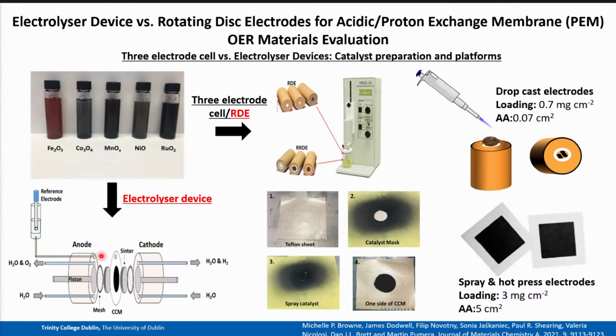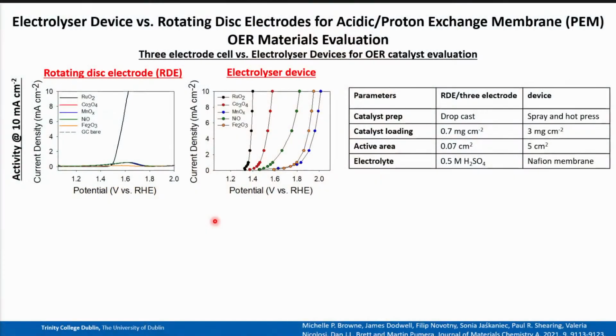So to directly compare the OER, so the anodic side of our electrolyzer device, to a rotating disc electrode, we used a reference electrode. So we were purposely just measuring the OER in the electrolyzer device. So for the results that I show you here, for your activity at 10 milliamps in the rotating disc electrode setup, essentially what we can see is that the ruthenium dioxide, which is also known as the state of the art, performs pretty well. However, for the first row transition metal oxides, they essentially all corrode once they get into the acids. And then for the same materials in an electrolyzer device, they all reach 10 milliamps per square centimeter, either before or at a potential of 2 volts versus RHE.